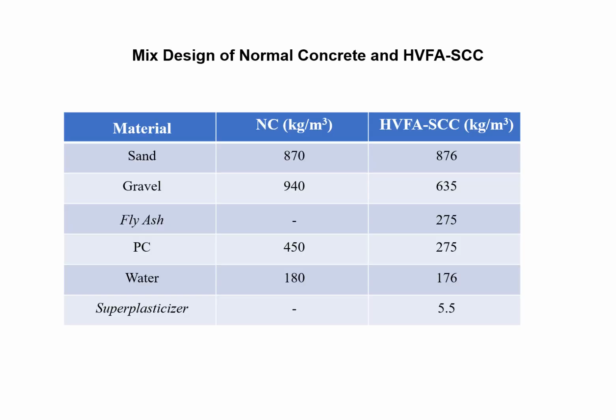Mix design of normal concrete and HVFA-SCC. For NC: sand 870 kg per cubic meter, gravel 940 kg per cubic meter, cement 450 kg per cubic meter, and water 180 kg per cubic meter. For HVFA-SCC: sand 876 kg per cubic meter, gravel 635 kg per cubic meter, cement 275 kg per cubic meter, fly ash 275 kg per cubic meter, water 176 kg per cubic meter, and superplasticizer 5.5 kg per cubic meter.